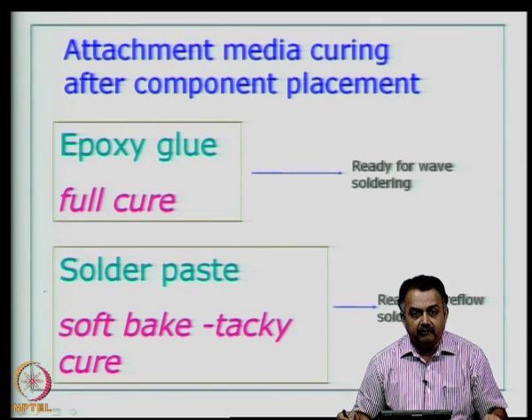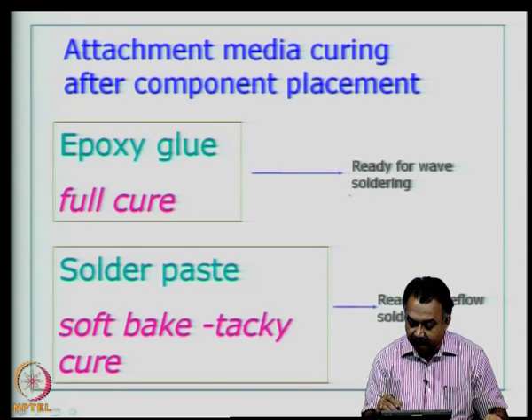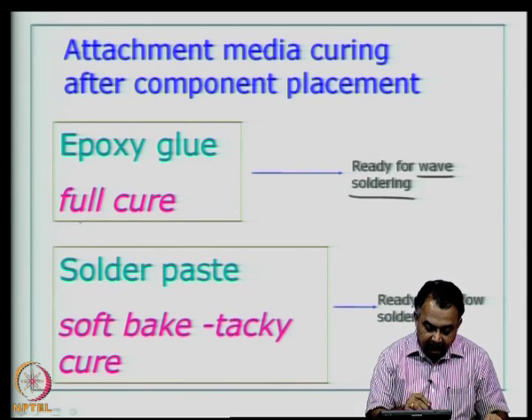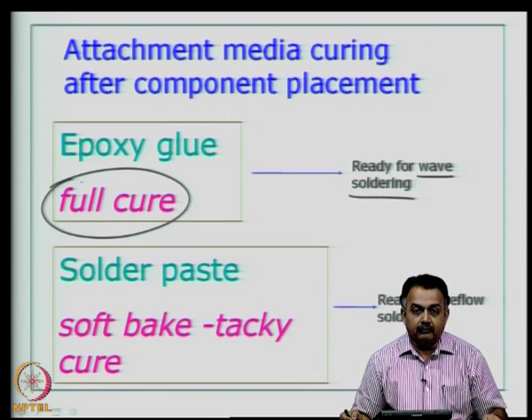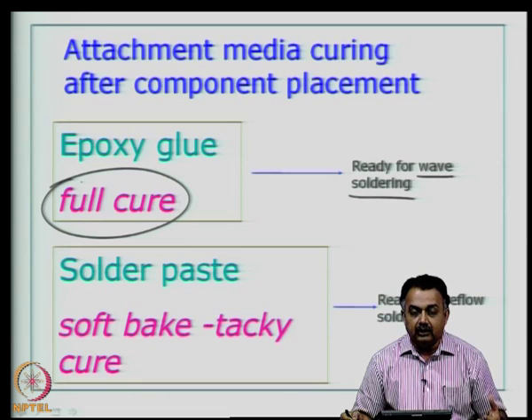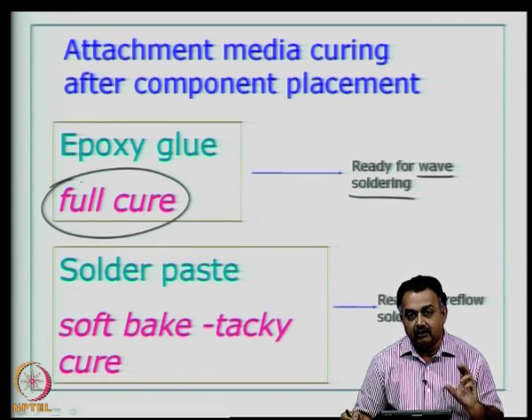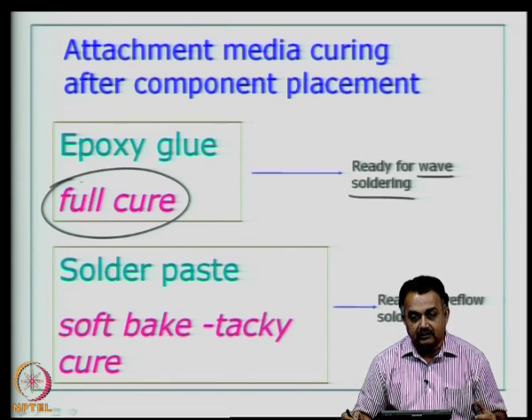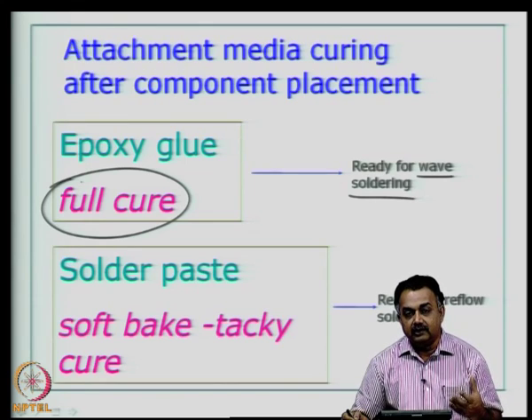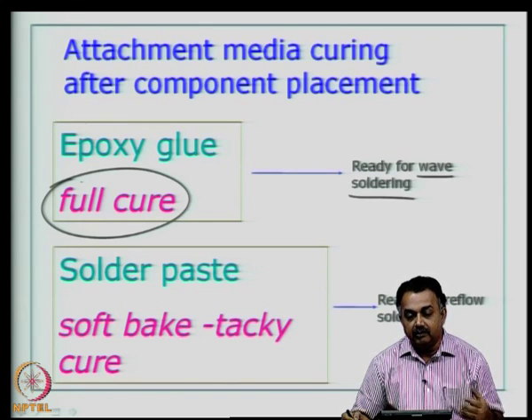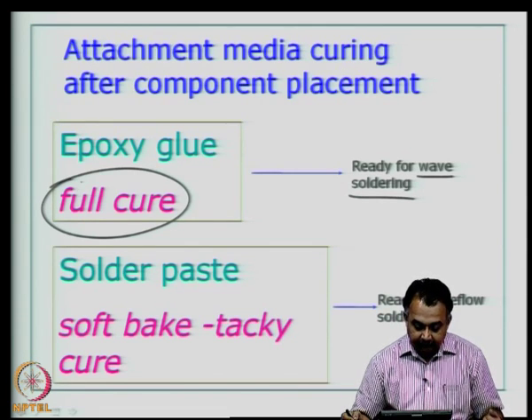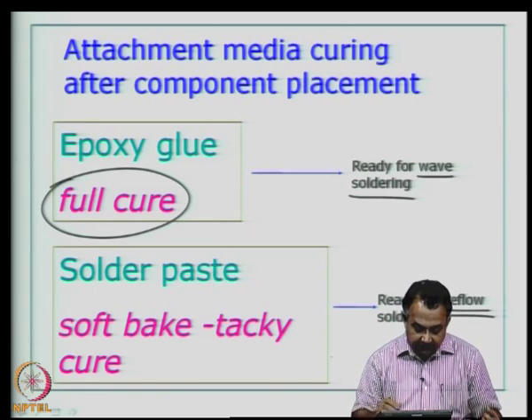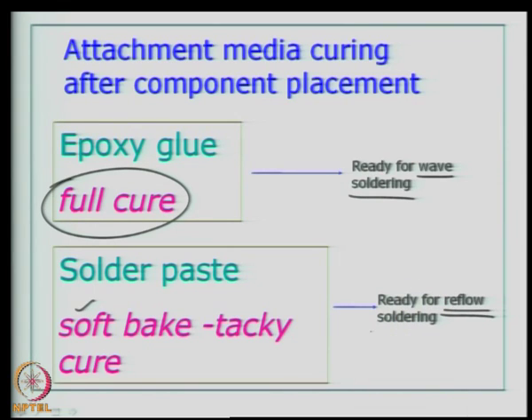If you have used an epoxy glue for wave soldering, make sure the glue is fully cured — not just tacky cured. Full curing ensures the component is held firmly on the board during wave soldering, and the cured epoxy will not be affected by the temperatures during the process. For solder paste in reflow, you use a soft bake — a tacky curing process — and the full cure takes place when the entire system goes through the reflow soldering equipment.